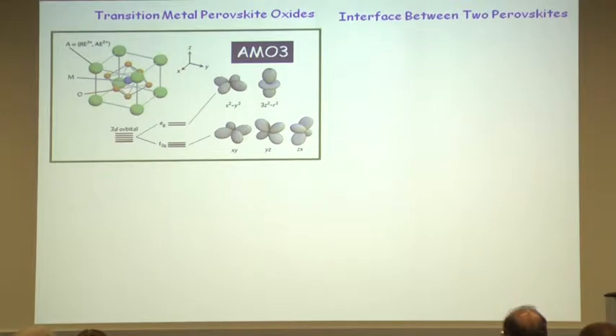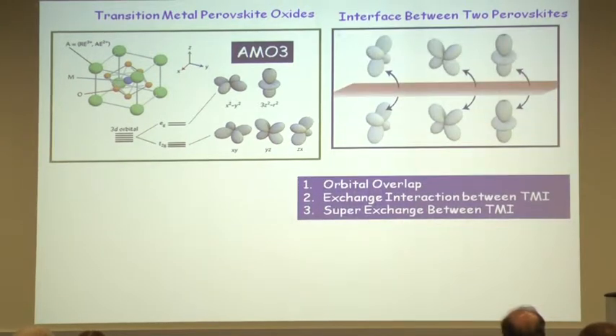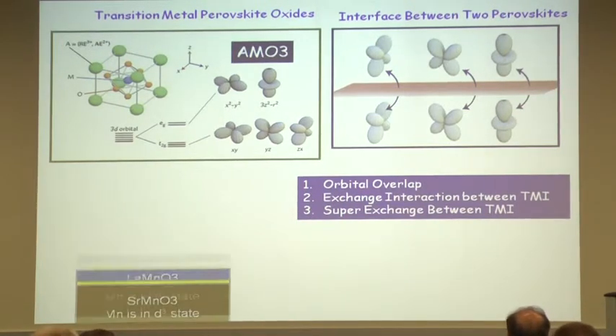role. Now, if I take two different perovskite oxides and create an interface in this manner, then at the interface, I can have a direct overlap between orbitals. And this direct overlap between orbitals can lead to exchange interaction between transition metal ions. And if you have some oxygen here at the interface, then you can also have a super exchange through the oxygen ions. And a beautiful example of that is here.